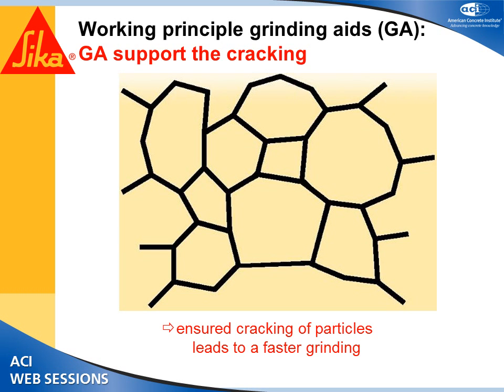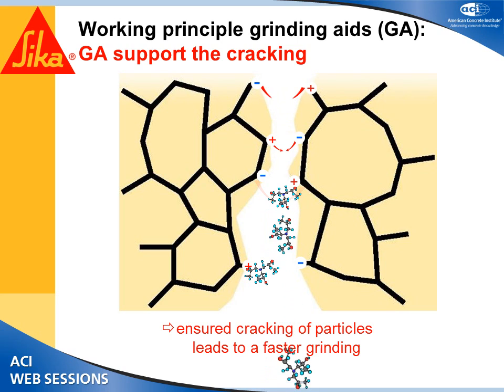And so how do these grinding aids work? In the grinding mill, when the steel balls are impacting the clinker, there's a crack formed, but within the crack there are these electrostatic charges which are attracting each other and try to bridge the crack. And when they bridge the crack, again now they have to be broken. So that decreases the efficiency of the plant and reduces the production.